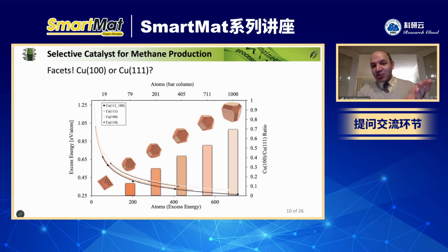At least from the DFT perspective, we showed that this particle 111 is more stable than 100. Because you can have a very small 100 cube, but we show that at that size, it's not stable. When it gets larger, yes, you see that the cube is more possible because the excess energy is lower, so it gets more stable. But at very small particle size, we couldn't get a stable 100 facet. So at the moment, I cannot be assured whether facet or particle size is important. I say both of them are important. They are related to each other.